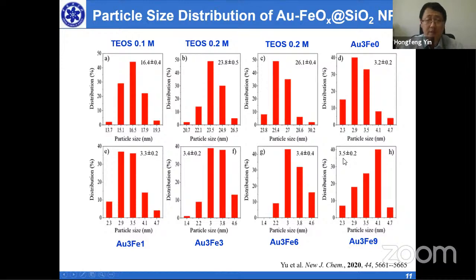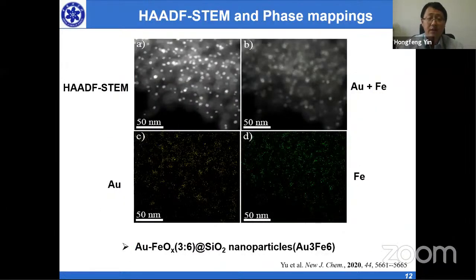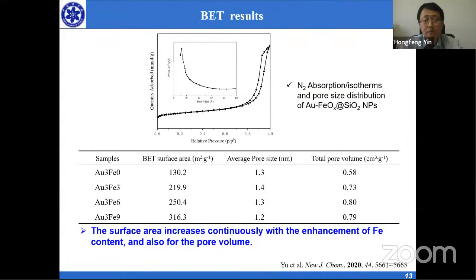There's no big difference. This is a mapping of the elements. You can see that gold and iron are mapped at the same position, so that indicates that the gold and iron have very good close contact.